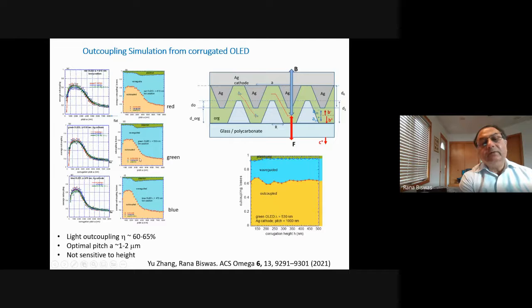Now, of course, if you have a large pitch, then it goes to the limit of a flat structure. And then you see the problem, you're back to about this 20% outcoupling, low outcoupling, and most of the light trapped in these wave-guided modes. Fortunately, this phenomenon is not sensitive to the height, as long as the height is more than generally about 100 nanometers or so. So this is a great boon for the fabrication.